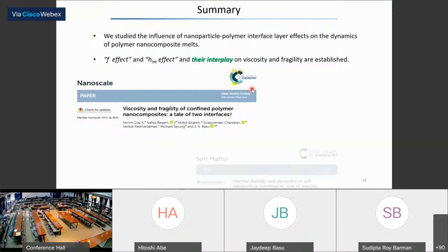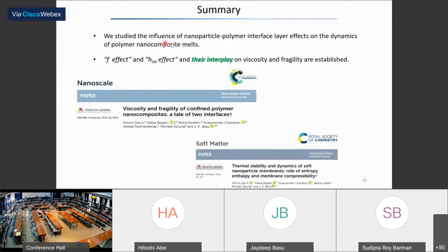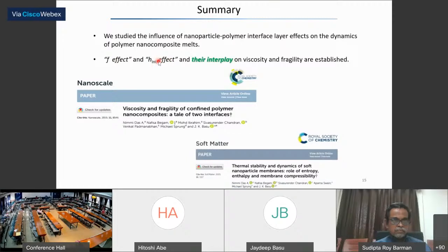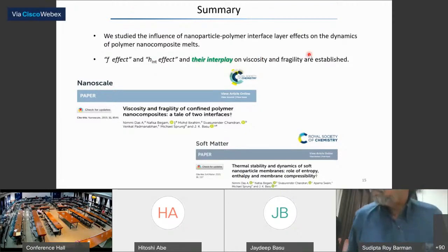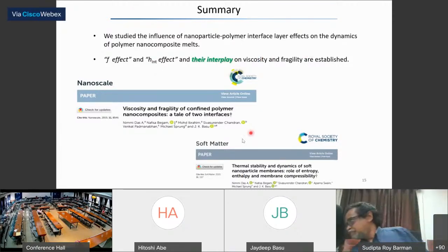I will summarize by restating what I mentioned: essentially this F, which is the interface between the particle and the matrix, and the H, which is between the film and the substrate, we are able to show how you can control this. So if you fix H, then by varying F, you can control viscosity or fragility, or if you fix F, by varying the H interface, you can control this. So that is something that comes out from this.